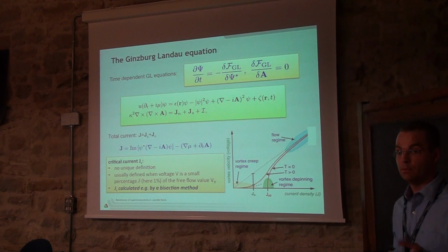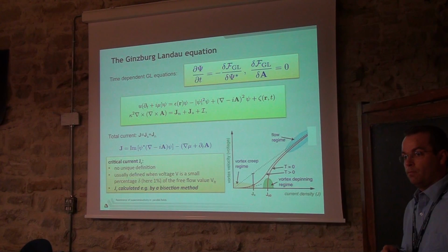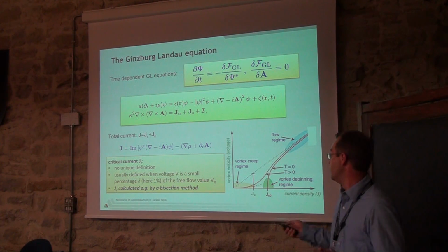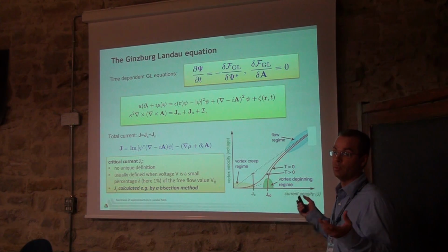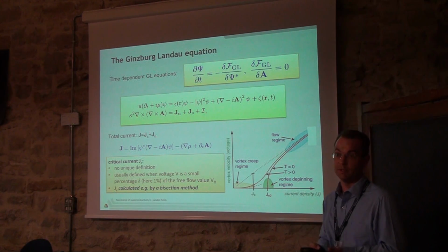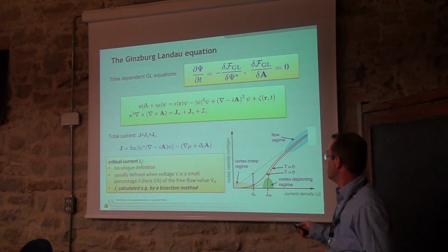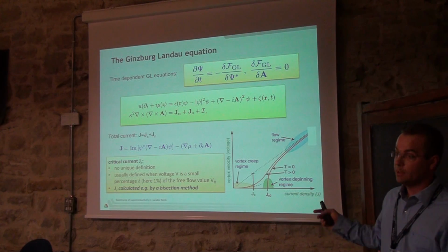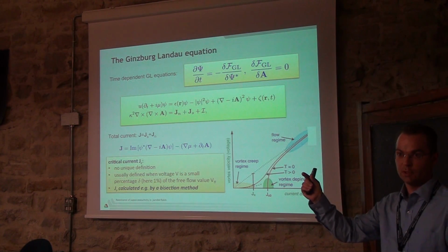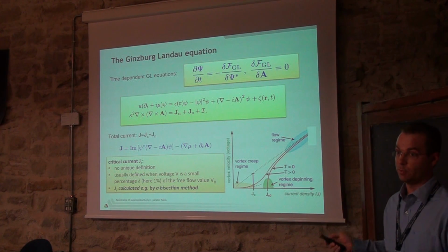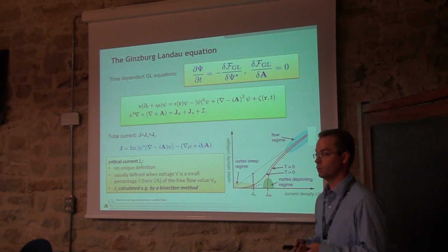Sorry, one question. How do you set the noise? Is it consistent with the fluctuation dissipation theorem or something like that? Yes, you can calculate the amplitude from the given critical temperature of the material. So this is determined by the material which you study. In this parameter here, you just fix the ratio between the temperature at which you study your superconductor and the critical temperature, but the absolute value of the critical temperature is encoded in the amplitude of the noise.